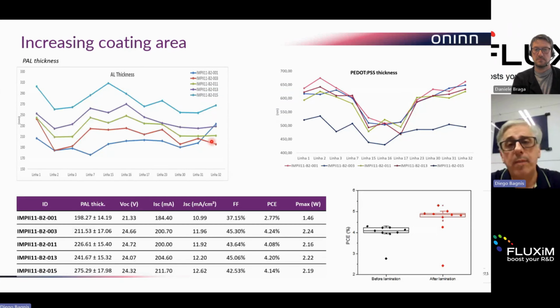and during the coating. But one of the main issues we got in the beginning was, for example, the PEDOT thickness, where there was a big drop, especially in the center line between 10 more or less till 20. So more or less 1/3 of the line was receiving less PEDOT thickness. Just to mention what we said until now: when you optimize everything for the small cell, you see the best condition, whatever the behavior of the material.